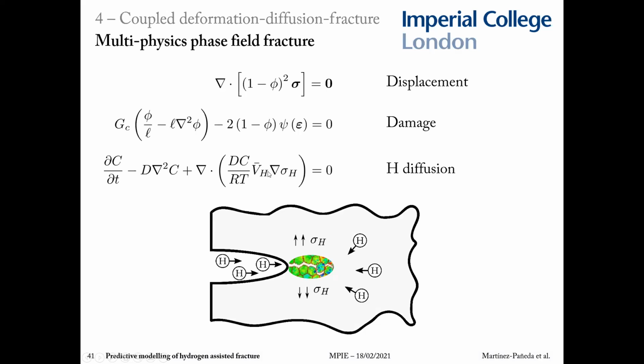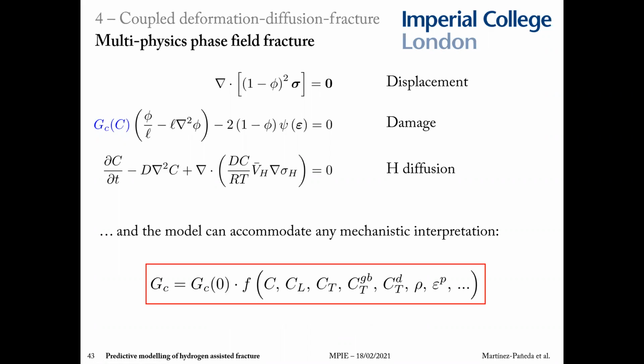So how do we couple the fracture and the hydrogen parts in this problem? Well, the big picture is very simple. What we know from experiments is that hydrogen reduces the toughness. So we just need to make our critical fracture energy or material toughness depend on the hydrogen content. How exactly does hydrogen degrade the material toughness? Well, that's the big question, I guess. And of course, each of us might have a different answer. The good news is that the model is universal in that it can accommodate any mechanistic interpretation.